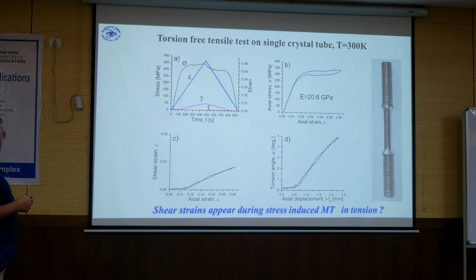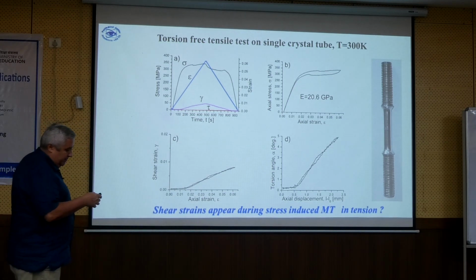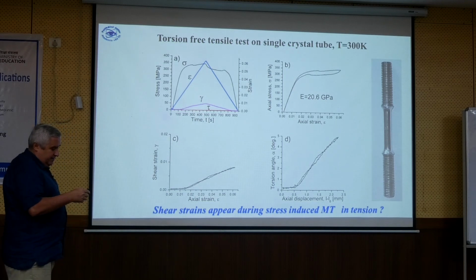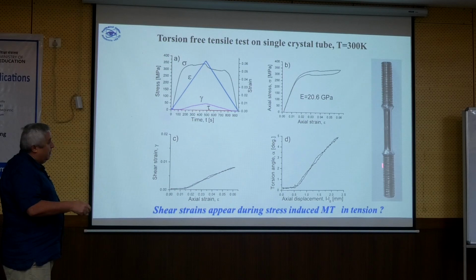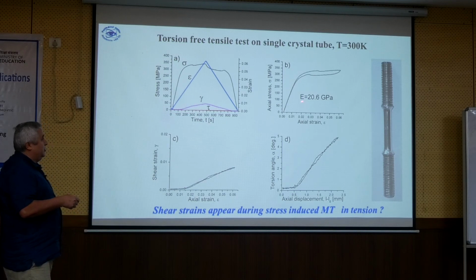Okay. Yeah, we did also one more very unique experiment because we were in Czech. We were able to make the copper, aluminum, nickel tubes. So this is like 10 centimeter size. So we made a sample which is a single crystal and could be deformed in combined tension and torsion. So we brought it to Japan, and in Japan we made this test.